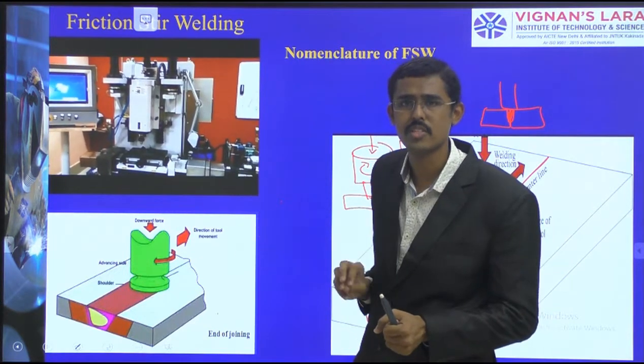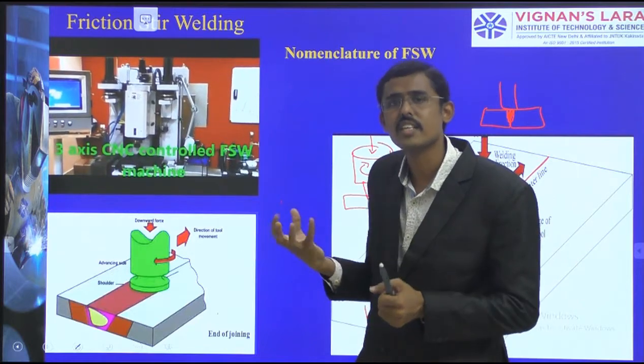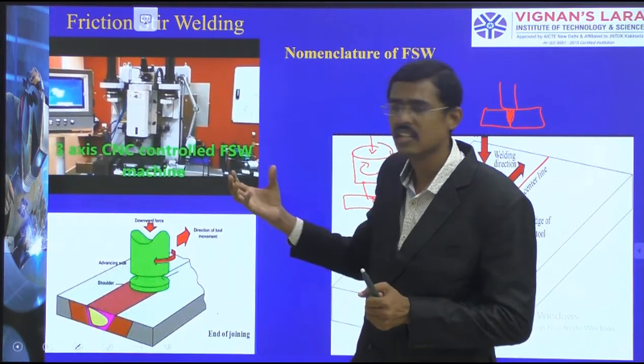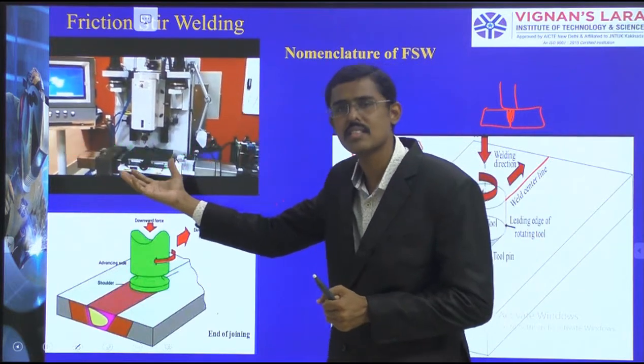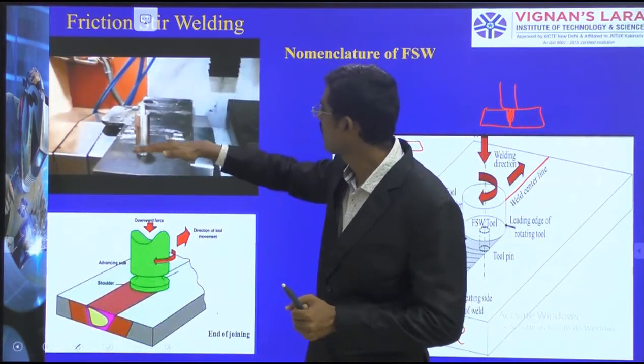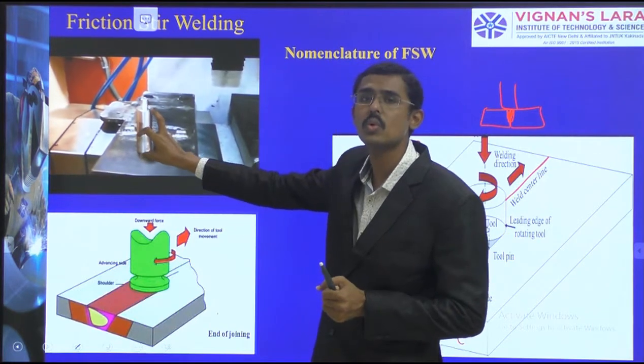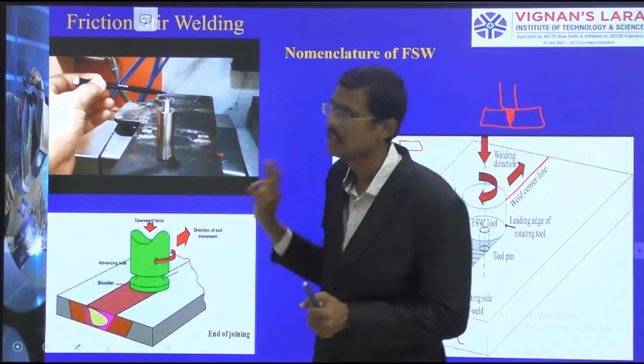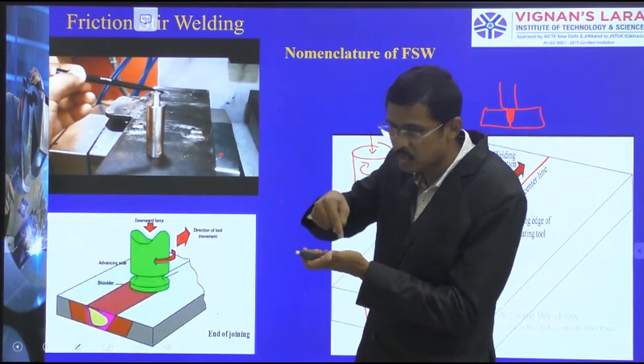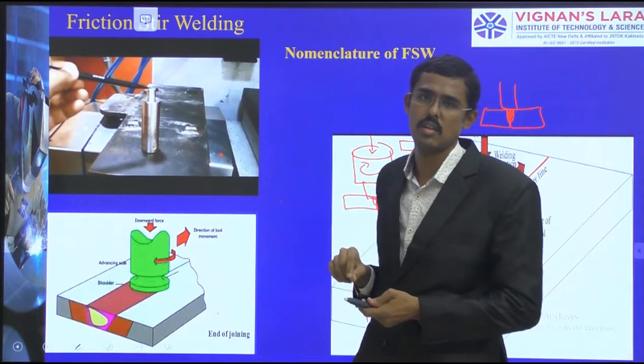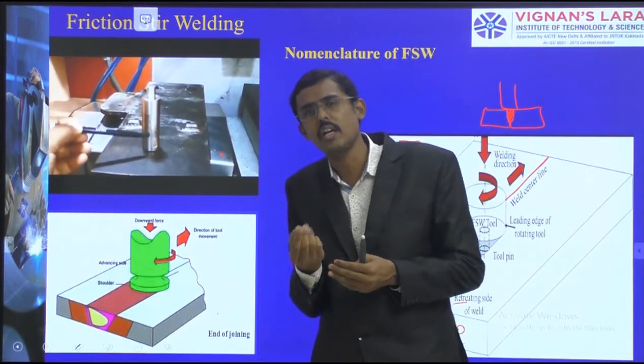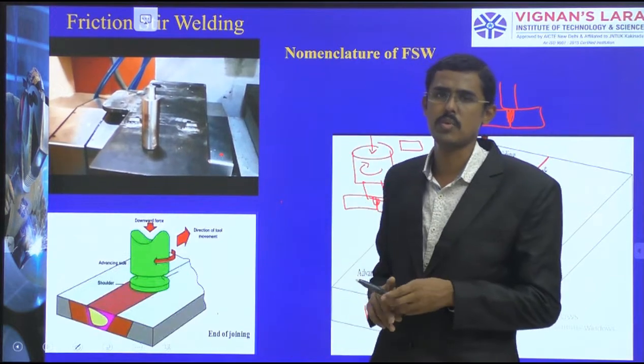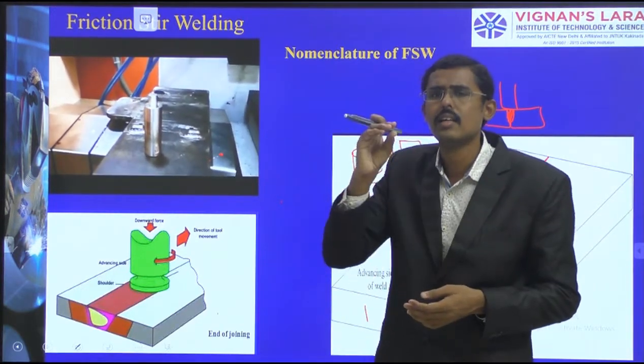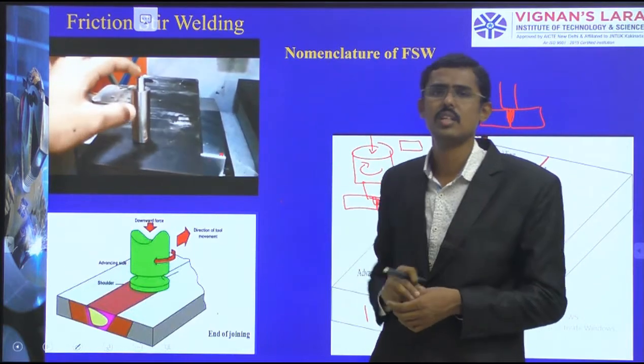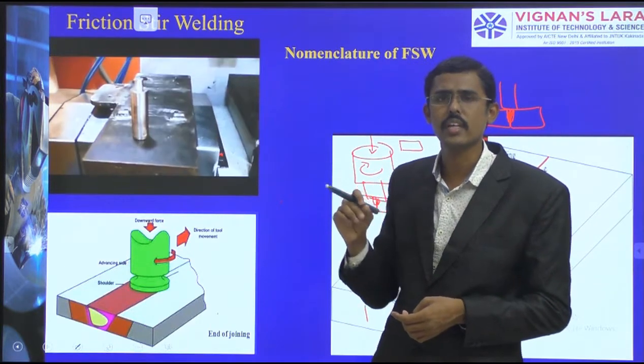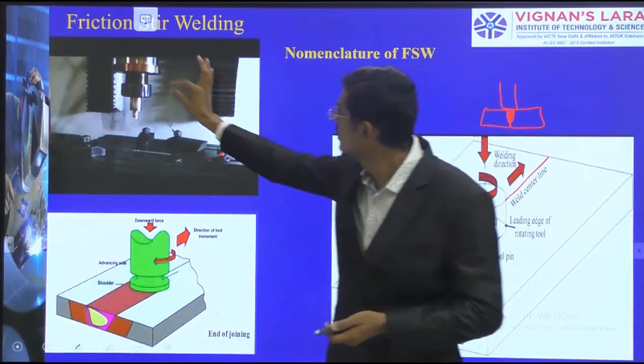This is the machine setup for the friction stir welding process, and it can be done on a simple CNC machine. We have a board and a setup, and we can do this. See how the tool is used. This is called the shoulder, and the pin goes in depth up to the total thickness of the specimen, not more than that. The pin profile should not go beyond the thickness of the specimen; it should be equal or slightly lesser. In the case of a 10 mm plate, we can take 9.8, 9.7, like that, for the pin profiles.